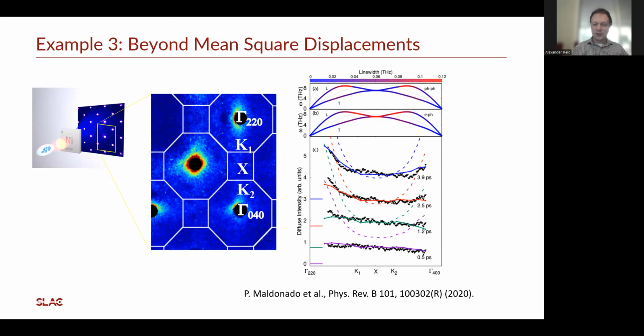By measuring this in a time-resolved measurement, we can see how those phonon populations are evolving. As a function of momentum across the Brillouin zones, we can see those phonon populations and how that system thermalizes. This was a study looking at the dynamics of the phonon populations after excitation in single crystal nickel.